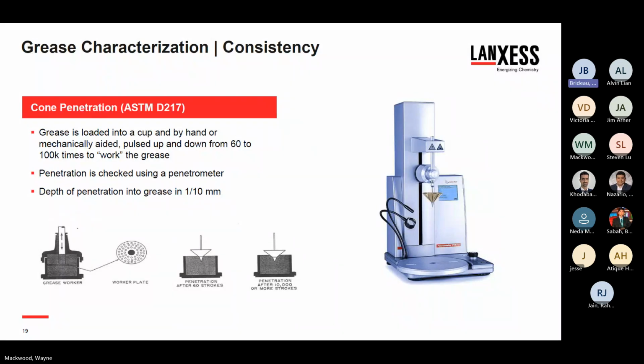Because it's a gelled product, you need some way to tell whether that amount of gelling is what you need for your application. And so that is what we call consistency. It's measured currently by a cone penetrometer. ASTM D217 is the most common. It's the full scale penetrometer. The depth of travel into that grease is the amount of penetration. And that penetration then is related to an NLGI chart.